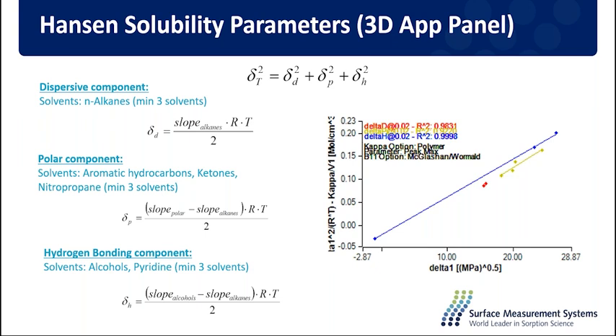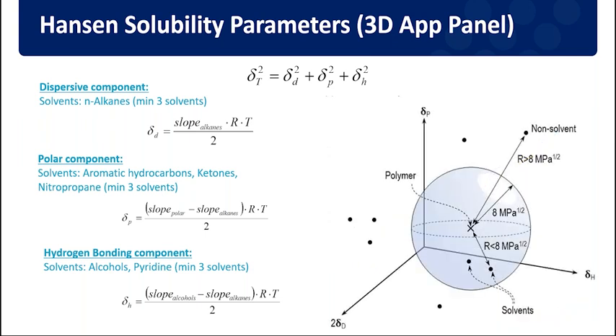has to be performed at the glass transition temperature of the polymer or the solid material. So it makes the applicability of the analysis a bit limited, especially in case of polymers or some materials. But in case of Hansen solubility parameter, the same concept as in case of Hildebrand. So once you measure the solid solubility parameter, there's a specified radius distance from that point, and every solvent which is in that sphere will be a solvent which is miscible with your polymer or solid, and everything outside will not.